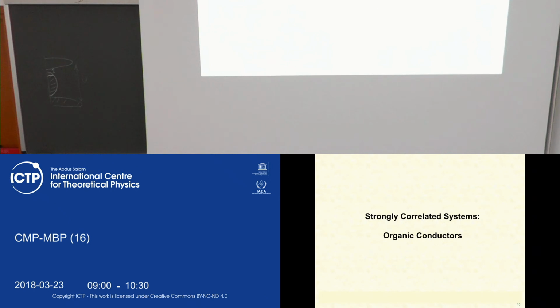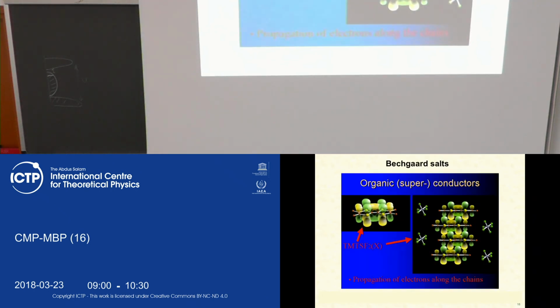Now we are coming to organic conductors and organic superconductors. These are typically quasi one-dimensional systems. In high Tc compounds we discuss quasi two-dimensional systems because copper and oxygen form copper oxide planes. Here it's basically organic molecules which are elongated in one particular direction. And again, in the early age of superconductivity, in 1964, Little and Ginzburg independently invented the idea that reducing dimension, namely coming to low dimensional systems, actually increases correlations and can lead to an increase of the temperature of the superconducting transition, and also lead to some non-phonon mechanism.